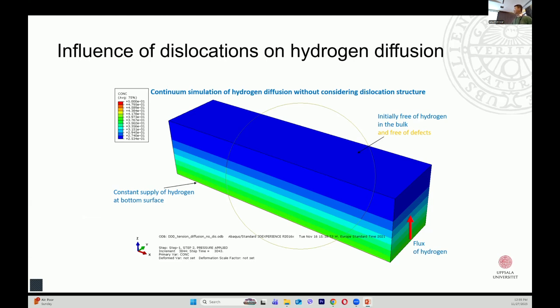So in this figure, I show the results obtained by the conventional approach, where we just use a classical Fickian diffusion. So hydrogen diffuses from the bottom upwards, and we consider the Oriani trap. Basically, we have a trap binding energy and density, and then we consider the trapping effect. In that model, all the traps are assumed to be homogeneously distributed across the volume. So it's smeared across the volume.